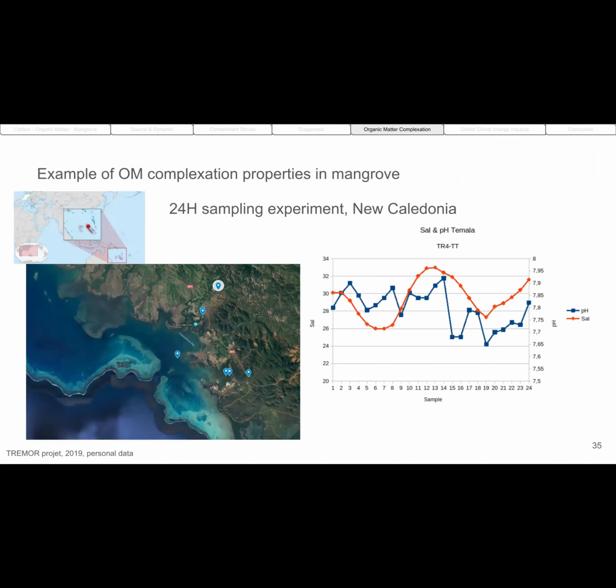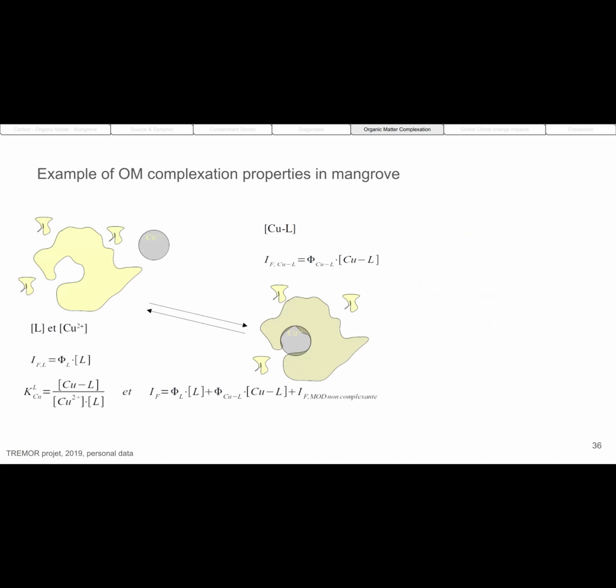I took an example from an experiment we did in New Caledonia. We sampled water over 24 hours that came out from the sediments, just at the output of the sediments. You can see here the salinity in red and the pH of the system. And from these samples, we made some quenching experiments. What is quenching? In fact, it's a way to investigate the interaction of metal with organic matter.